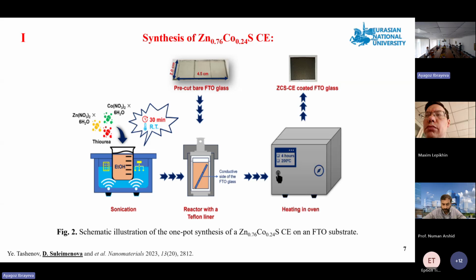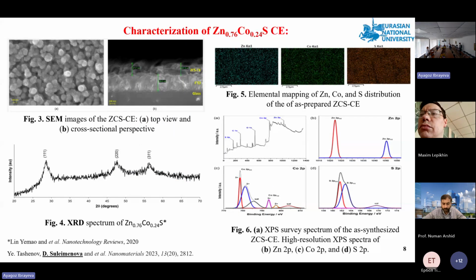On this slide, you can see the characterization of zinc cobalt sulfide counter electrodes. SEM analysis shows spherical particles around 100-150 nanometers forming clusters at the micro scale with a nanoflake-like structure. The film thickness is approximately 465 nanometers with a smooth and uniform surface. XRD analysis shows three main peaks assigned to the cubic phase of zinc cobalt sulfide, which is consistent with literature data. EDS analysis demonstrates the presence of zinc, cobalt, and sulfur, as well as their uniform distribution over the electrode surface. XPS confirms the composition and oxidation states of the elements: zinc 2+, cobalt 2+ and 3+, sulfur 2-, and shows small amounts of oxidized sulfur.